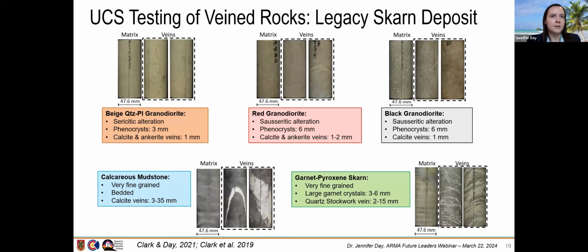The calcareous mudstone was very fine-grained, bedded, and had calcite veins that varied widely in their width, from 3 to 35 millimeters. You can see one of the widest veins in that photo on the slide. The garnet pyroxene skarn was a little bit different, where it had a quartz stockwork vein network at the lab sample scale. In all of the other 4 lithologies, we were able to isolate single inclined veins in our lab testing. But for this garnet pyroxene skarn, it gave us an opportunity to test a vein network, which means we can't just look at a single vein at a time. Another part of the garnet pyroxene skarn is that there are very occasionally large garnet crystals in the matrix, about 3 to 6 millimeters.